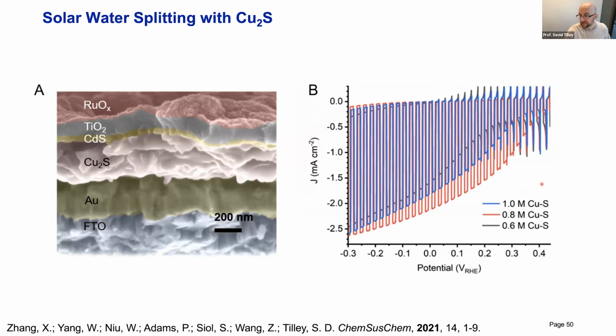And so these are just different concentrations of this ink solution, and we can see that, at least with this intermediate value, we get quite a nice fill factor, let's say, and also decent currents. Considering that we have such a very thin film, which is not absorbing a lot of light, this is a high current.